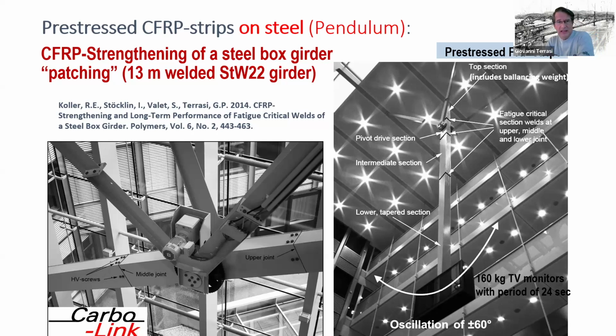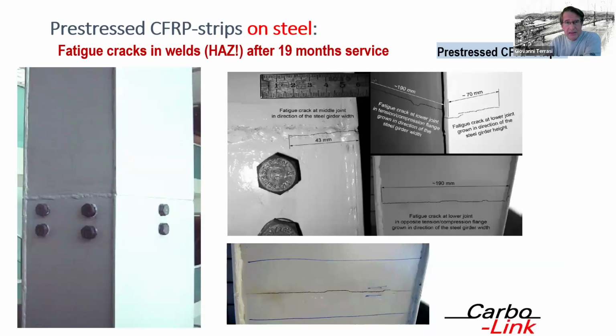But unfortunately, in the heat-affected zones of those welds, after 19 months of service, back in the year 2003, we had dramatic fatigue cracks, which are shown on the next slide. You see here the heat-affected zones, well known to be the weak links in fatigue for a welded steel girder. Here we had dramatic cracks, and even the heads of single screws were falling down in the entrance hall. Not really good publicity for a reinsurance company, which then stopped the pendulum and asked EMPA for a refurbishment option. And here we teamed up with Carbolink.